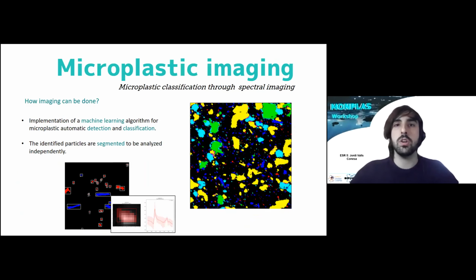And finally, in terms of microplastic imaging, using those hyperspectral images obtained by QCL and FTIR, we can use an imaging method in order to classify and detect the microplastics inside the sample. To do that, we use a machine learning algorithm that is trained using microplastic spectra in order to classify each pixel of the image as any kind of microplastic.